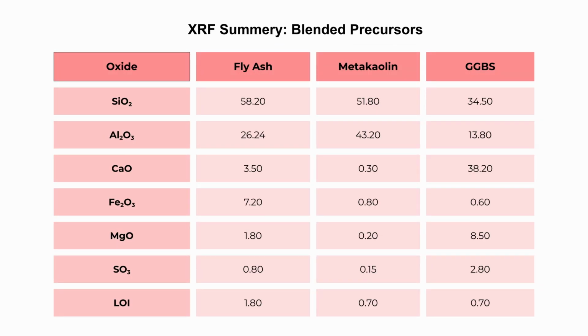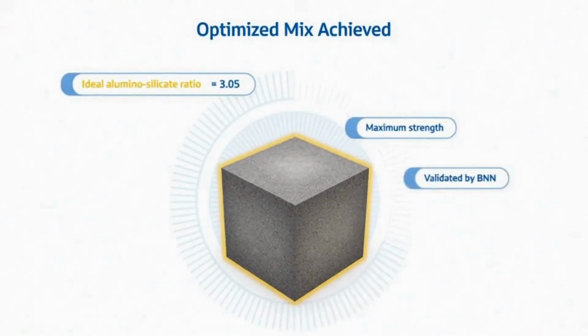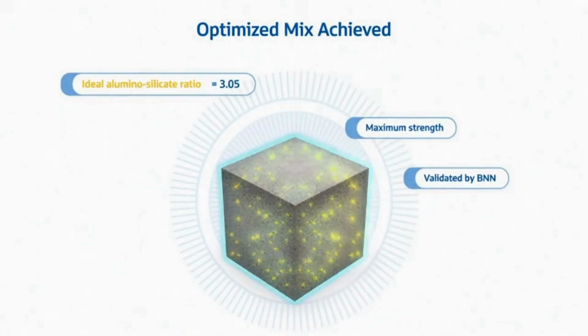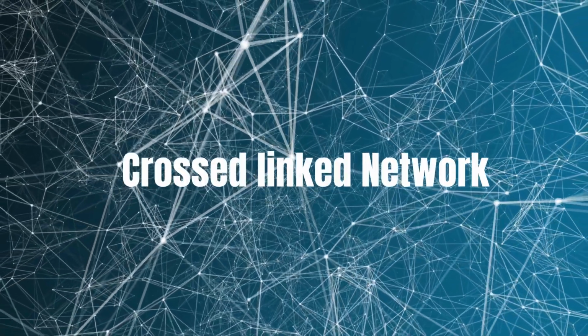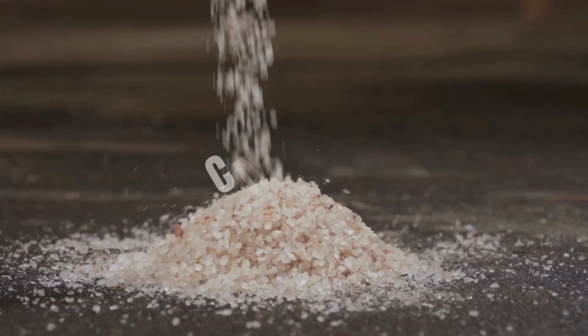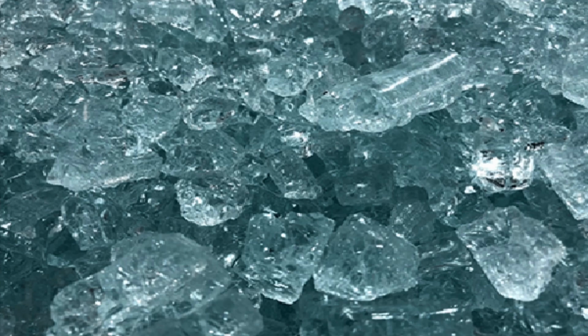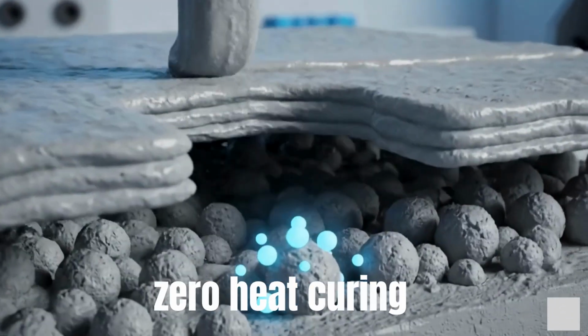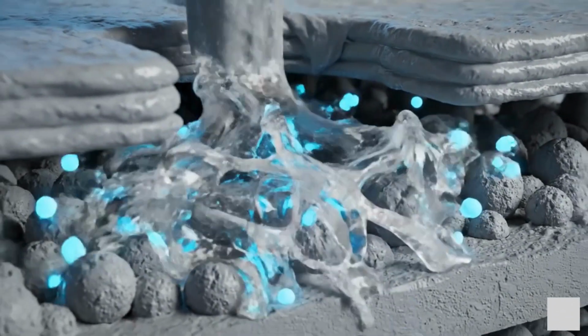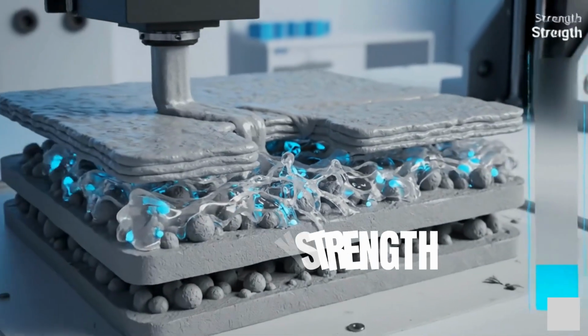Using XRF, the geopolymer system uses an exact silica-to-aluminum ratio of 3.05, ensuring a dense cross-linked network for strength and durability. The GGBS in the precursor provides calcium oxide, enabling rapid C-S-H gel formation at ambient temperature. This allows ambient curing without heat, while offering early strength and controlled setting suitable for 3D printing.